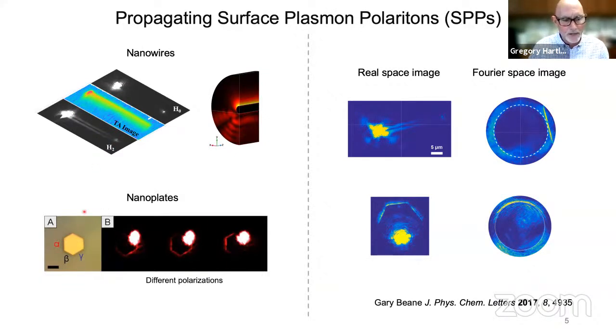Okay, so these are the two different plasmon modes that happen in a wire. These images over here at the bottom are the same sort of thing for some nanoplates. You have a laser focused on the edge and you can excite plasmon modes in the nanoplate that move across the plate. When they get to the edges, they emit a bit of light. Okay, so for a resonance, what you measure are a resonance frequency and a line width, and the line width gives you the lifetime information. For these propagating modes, what you can measure are the propagation length and the wave vector. And it turns out if you take those two measurements, you can also get lifetime information.